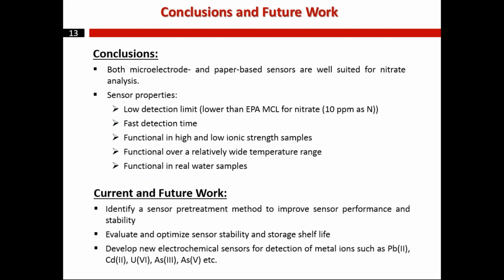So in conclusion, we showed that both microelectrodes and paper-based electrodes can be used for detection of nitrate. Both of the sensors appear to have a low limit of detection and fast response toward concentration of nitrate. The sensors could be used in both high and low ionic strengths, and they work independent of temperature of water. Therefore, both of the sensors can be used for detection of nitrate in real-world samples.